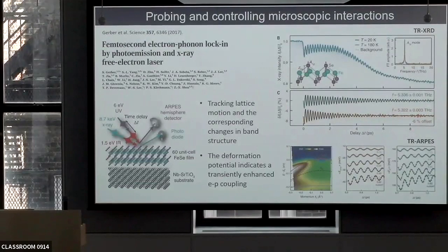The oscillations are associated with a phonon, which has to do with the motion of the selenium atoms with respect to the iron atoms along the z-axis. If you transform them, they correspond to one particular frequency, so one particular mode being excited. In parallel, you can do an experiment where you shine the same pump energy, 1.5 eV, and now you probe it with a UV pulse, and you see what happens to the band structure. So it's a combined time-resolved X-ray diffraction and time-resolved photoemission on the same sample.